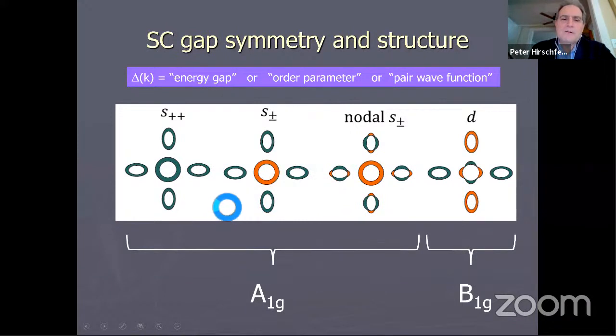You can have what's now called an S++ state, where on each of these Fermi pockets, I hope you can see my cursor, the sign of the superconducting gap is exactly the same. Magnitude can vary, but the sign is the same. S plus minus is another state that comes into contention, as I'll show you, where the sign as designated by the color is different on the central hole pocket and the exterior electron pockets. I forgot to say that the outer pocket has electron character and the inner pocket has hole character.